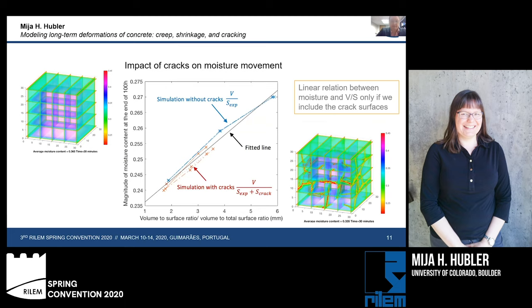We can take this type of data, the spatial data of our crack distributions, and introduce it into a moisture diffusion model and check whether the impact of cracks on the moisture movement is in fact related to the volume to surface ratio, as it is currently often captured in creep and shrinkage prediction models. What we find in the case here on the left, and in the plot in blue, is that if there are no cracks, then we can relate the magnitude of the moisture content at a certain time to the volume to surface ratio in a quite linear fashion.